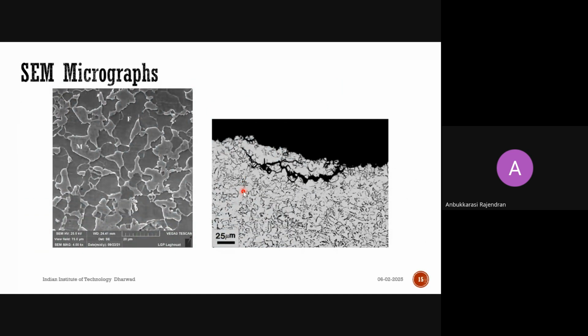Okay, so whatever we are seeing in the optical microscope, if some features are finer, we cannot make them out clearly. In such cases, we need the help of another tool which can magnify and reveal the features clearly. The scanning electron microscope is one such tool, which can magnify features up to 2 lakh times their original size, right? This is one of the micrographs from a multi-phase steel, with ferrite, martensite, and some bainite. It cannot be clearly revealed by optical microscope. So with the help of SEM, we try to distinguish the phases and confirm the phases present in the sample.